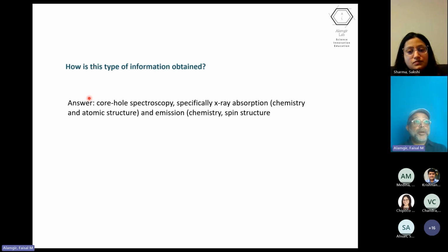X-ray emission gives you some details of the spin distribution that is harder to obtain from the other experiments. But the only technique here that gives you a very direct way of looking at the atomic structure is the X-ray absorption technique. So the combination of X-ray absorption and X-ray emission is actually quite powerful. But the other part of this, the reason I'm only highlighting absorption and emission rather than also, let's say, X-ray photoelectron spectroscopy, XPS, is because these two techniques, XAS and XES, are X-ray photon in, X-ray photon out type of techniques. In other words, the penetrative power of the X-rays is something that we can benefit from.